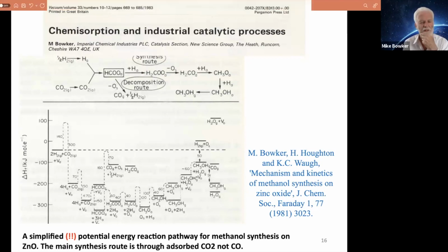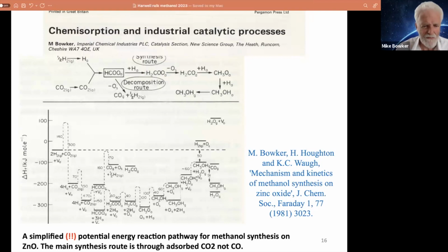Obviously, if it's on a surface like zinc oxide, as this one is here, vacancies in the presence of hydrogen are likely to play a big role in the catalysis. We'll say a bit more about this later, but you can see the vacancies are there in the presence of the formate, the hydrogenated formate, but then the vacancy is filled by the oxygen atoms from the formate when it drops an oxygen and makes the other species, single oxygen species.